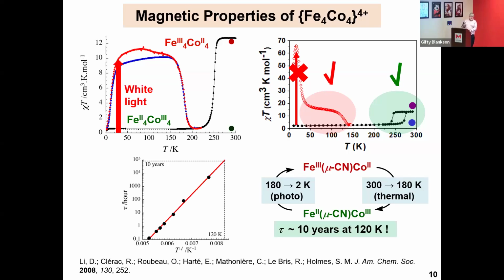And so for the first time, we showed that we could access the two states photochemically and thermally. We have a lifetime of 10 years at 120 K. That may not be of much importance to you, but I mentioned that magnetic hard drives have a lifetime for their data storage of 10 years, albeit at room temperature. If you compare the molecular box that I was just describing to the three-dimensional Prussian blue analog, the molecular box has a lifetime of 10 years at 120 K, but the Prussian blue analog is 3 days. So 8 metal centers does a better job than a million. Talk about atom economical.